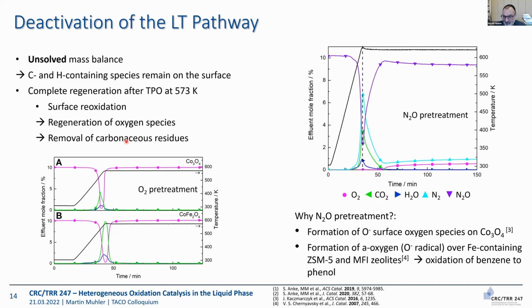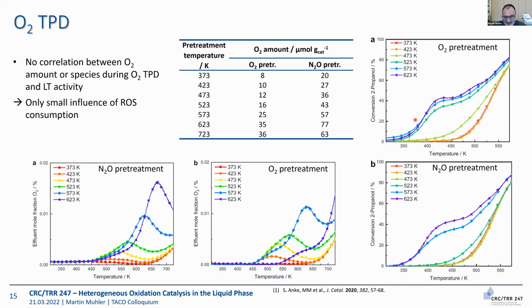Actually not that surprising. Then we were wondering, is there a difference when we regenerate in oxygen or when we make use of N2O that actually comes from zeolite catalysis? N2O decomposes into N2 and O, so then you get atomic oxygen. So we wanted to check, is there a difference between molecular oxygen and atomic oxygen? And we found out, well, in principle, yes, but it's not that important. We can regenerate in both gases. We can regenerate in oxygen. We can regenerate in N2O. The reactivity is a bit different. O2 is more reactive than N2O. And you see immediately, okay, the low temperature channel reappears in N2O. We have to heat a bit higher to 573 K, 300 degrees C, whereas in oxygen it's sufficient to heat to 523 K. So both gases can regenerate.